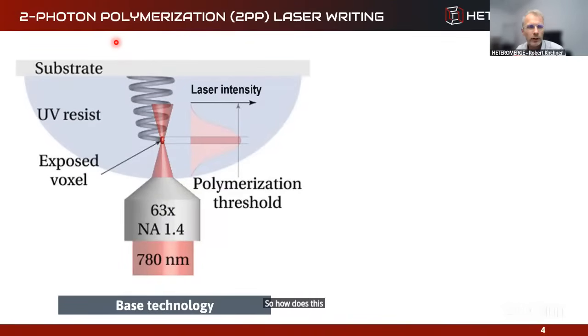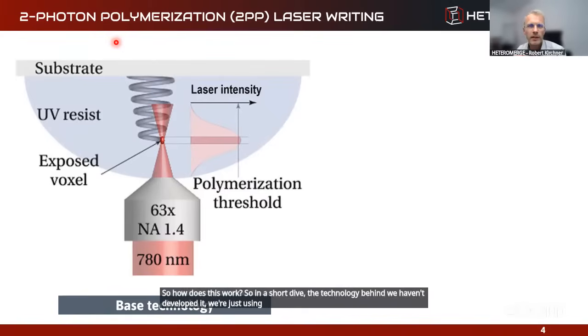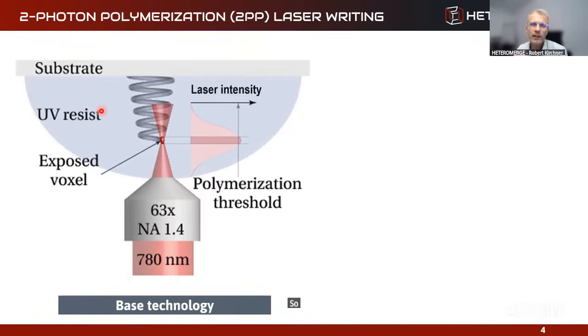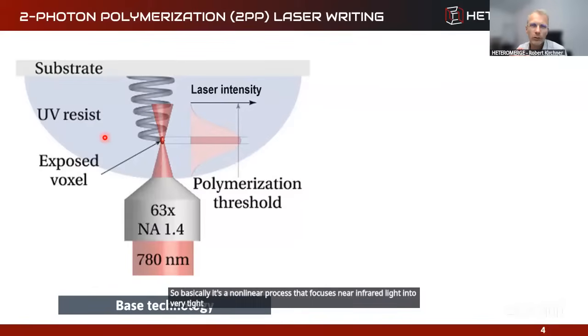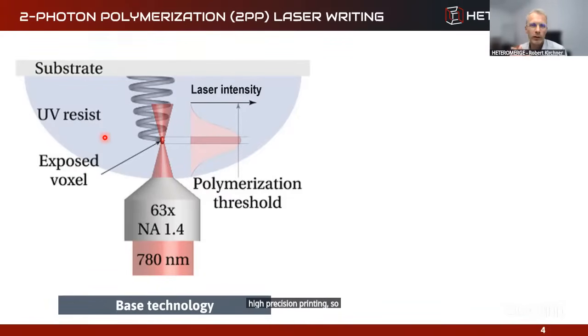In a short dive, the technology behind it, we haven't developed it. We're just using the printers. Basically, it's a 2-photon polymerization process. It's a nonlinear process that focuses near-infrared light into a very tight volume, also called a voxel, and that triggers a nonlinear process where you get from this near-infrared light a polymerization in the UV range, with line widths in the range of 100, 150 nanometers. You get very high precision printing, so you can really print optical quality surfaces.